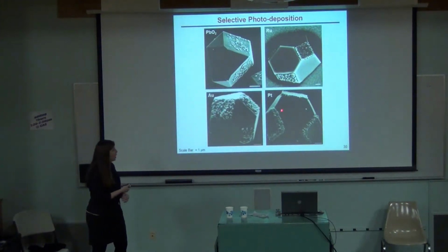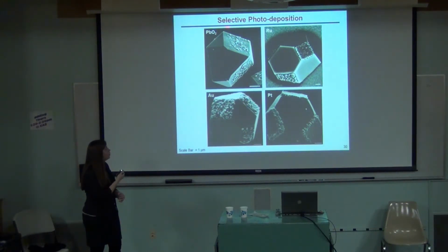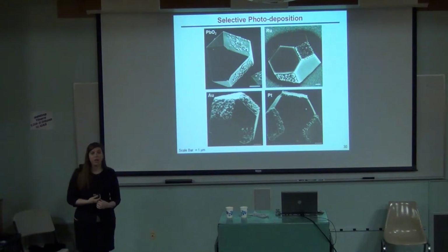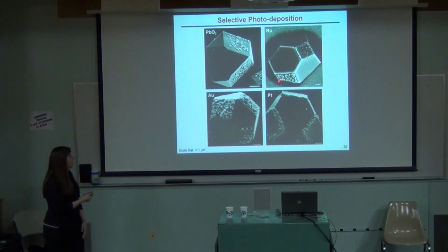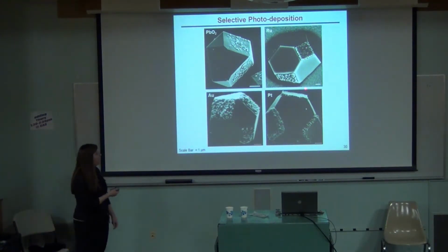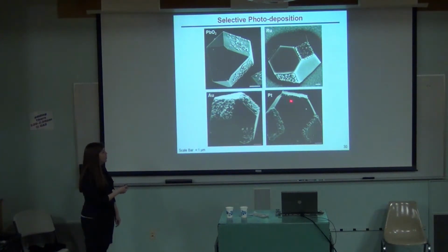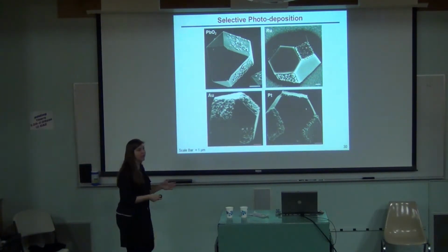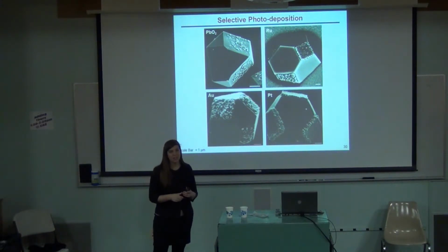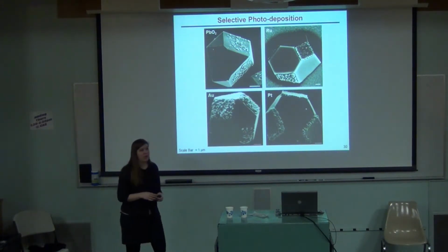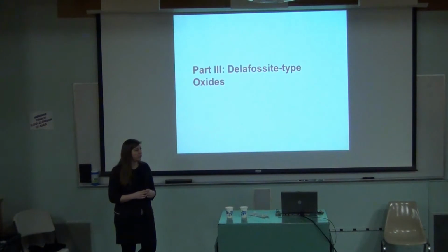So this is just to show you that even when I deposited what should have been, so lead oxide should have gone on the one plane, it didn't. Everything went on there. And the platinum, you can tell how selective this is, this picture's a little bit dark, but it just keeps getting thicker and thicker. It does not want to touch the 111 plane, which means that there's something there that is really impeding that. And I think that's an interesting phenomenon that I want to look into more in the future.